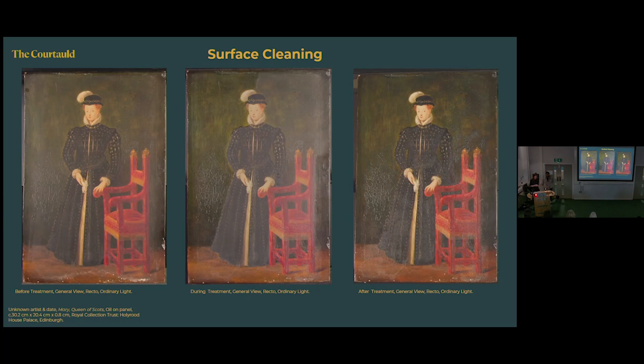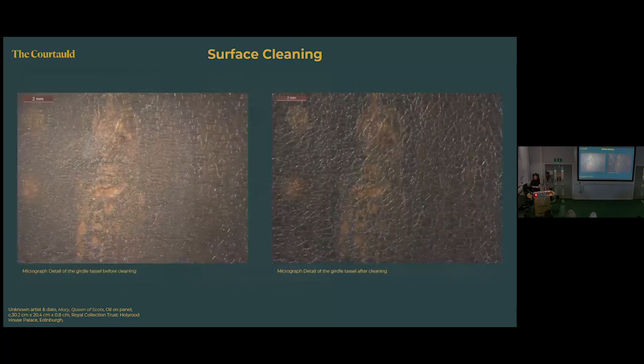This treatment really did very effectively remove a large majority of the surface dirt and has allowed a much clearer analysis to be conducted. It's especially evident under the microscope, which, as you can see, the surface dirt did obscure the painting, although, as is also apparent, the surface is still partially obscured by a very crazed varnish which has cracked and, especially in the darker passages of paint, has caused light scattering to somewhat disrupt the image still.